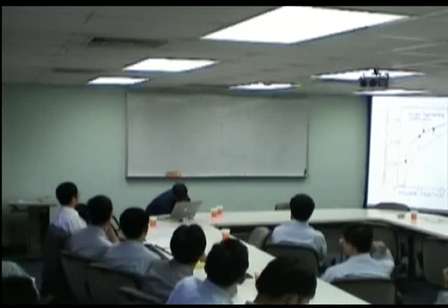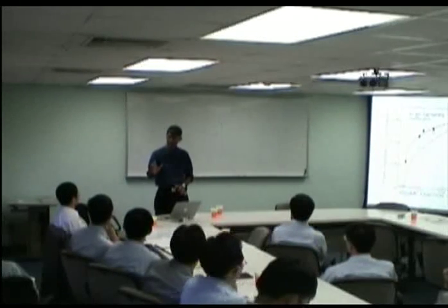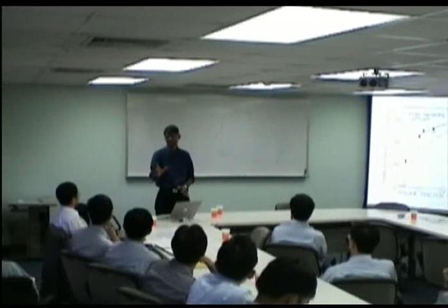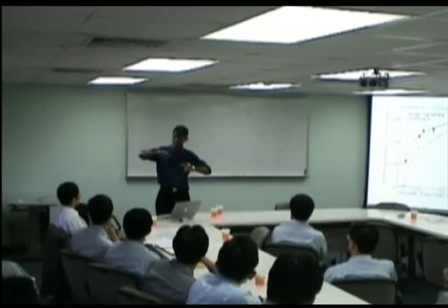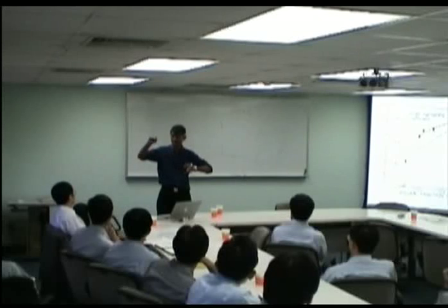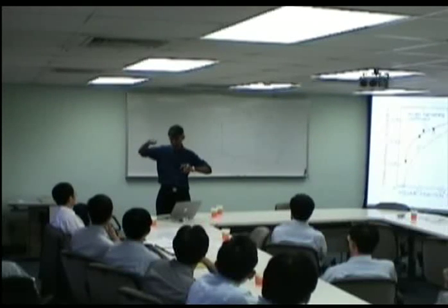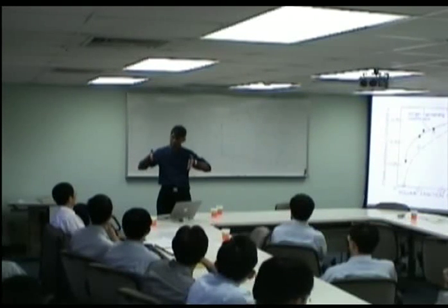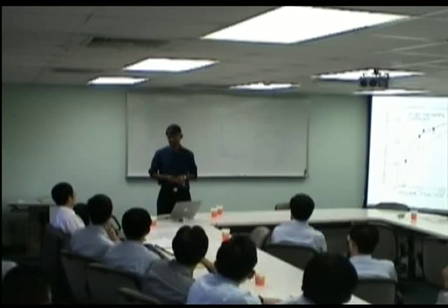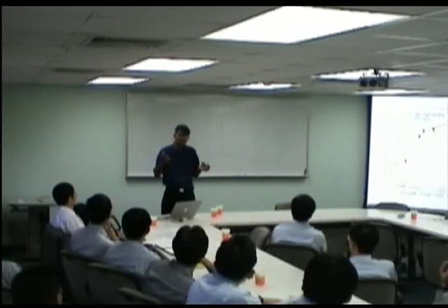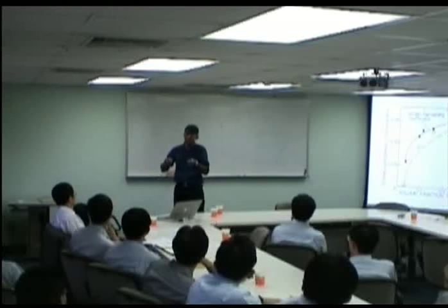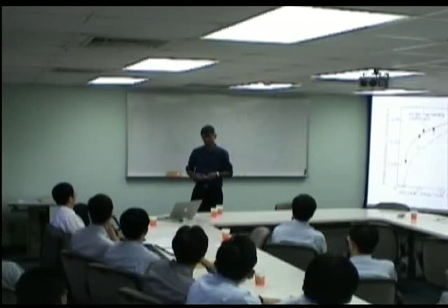Final ductility, you cannot predict, but the uniform elongation you can, because you've got this Considère construction, which tells you that at some point you'll get a drop in the tensile stress. So the uniform elongation part you can predict, but the final elongation depends on things like void nucleation and it's just too messy.